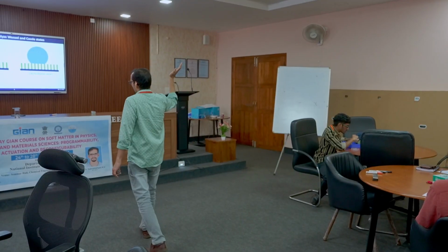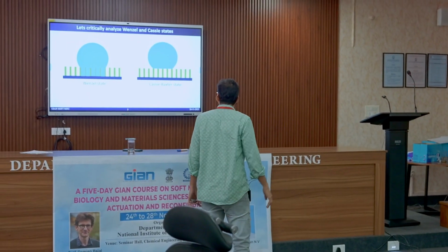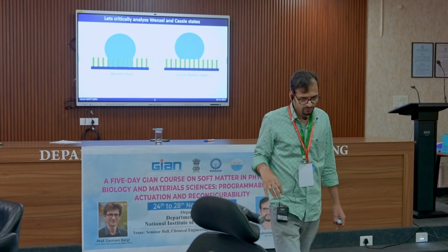So then let us critically analyze the Wenzel and Cassie models. Even with that, the projected surface area, we discussed that in the first lecture, right? So this is how it works, right? So you have actually, I would say, the lotus leaf on the right side, and this is another point you have to take care of. The material with which we fabricate the structure is also important. So in the case of the lotus leaf, there is a wax coating on it, not only due to the structure, and the one we see is actually microstructures. But in addition to that, there are even smaller structures present. So what we see is a collective effort of all these features.